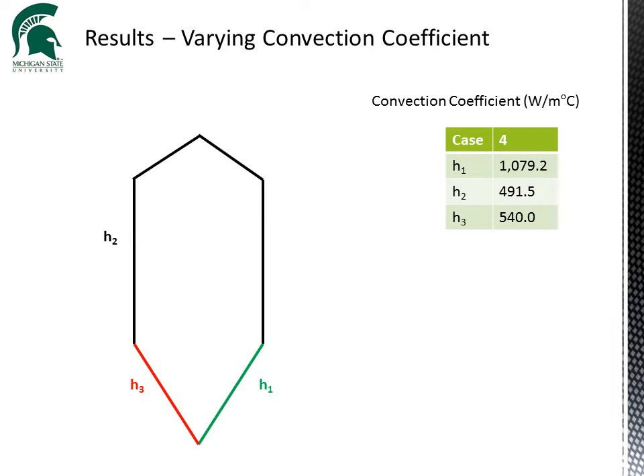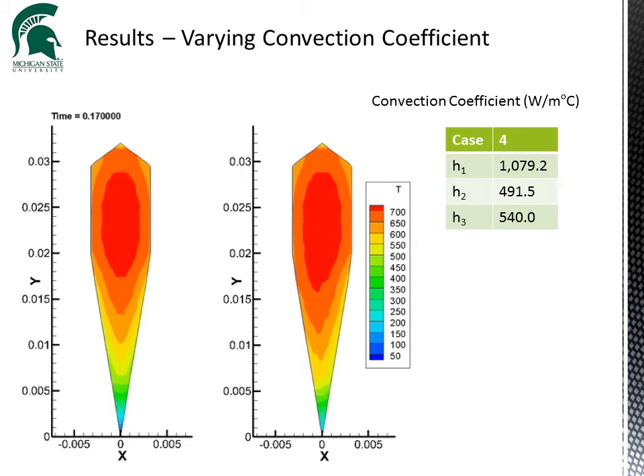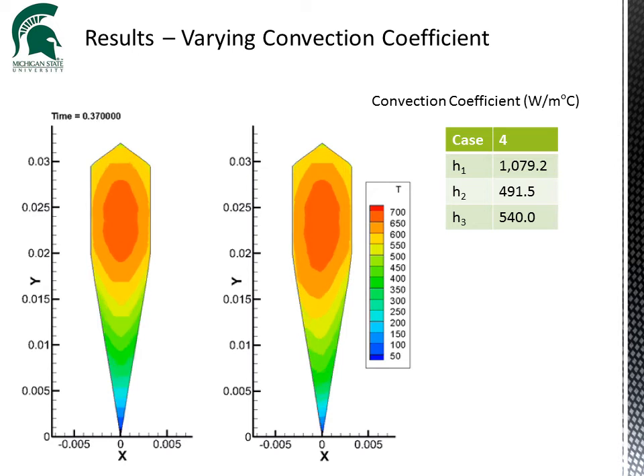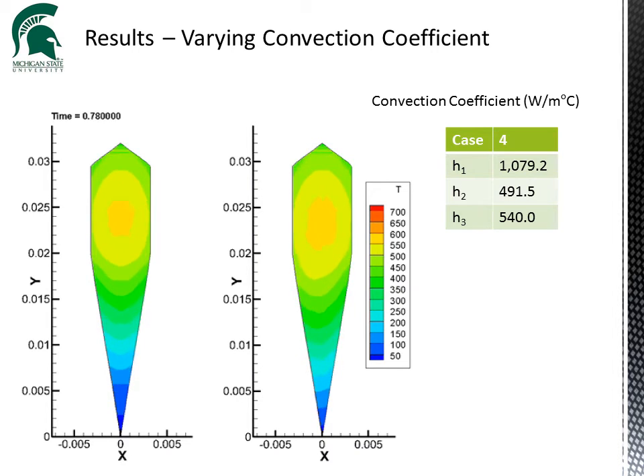Now, if the sword forger had a bad day and decided to use more insulation on one edge, you can see that there develops a very asymmetric temperature distribution in the sword cross-section. Now, although the temperature distribution does seem to be relatively uniform, you can see this asymmetry developed, which will impact the sword properties.